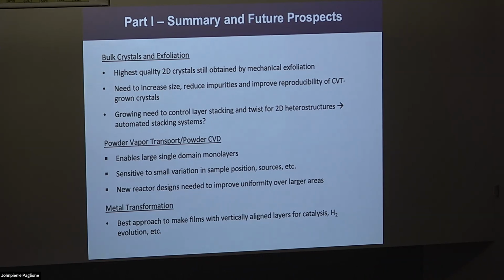So what's the substrate that you're using? Oh, okay. So far, none of this is epitaxial. So it's actually silicon dioxide. It's like an amorphous surface. So you can do this on silicon dioxide because of the weak interaction between the layers and the surface. But you don't have any registry, no orientation control. And so it's hard to get films that are single crystal.